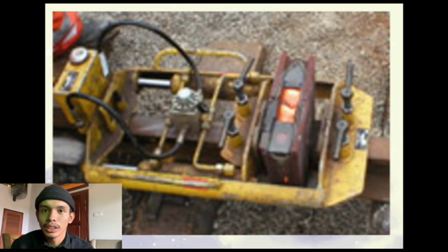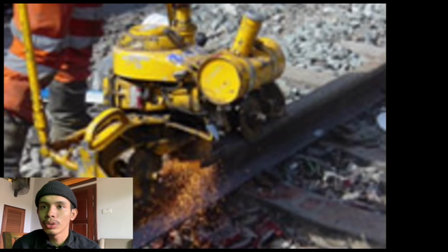The welded joint is allowed to cool for a predetermined time before the excess steel and the mold material is removed from around the top of the rail with the aid of a hydraulic trimming device. When cooled, the joint is cleaned of debris and the rail running surface is precision ground to the profile. The finished weld must be inspected before it is passed as ready for service.